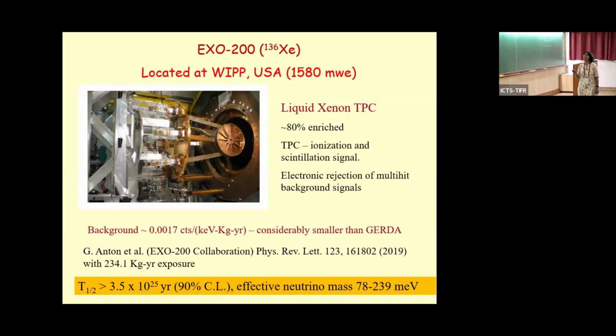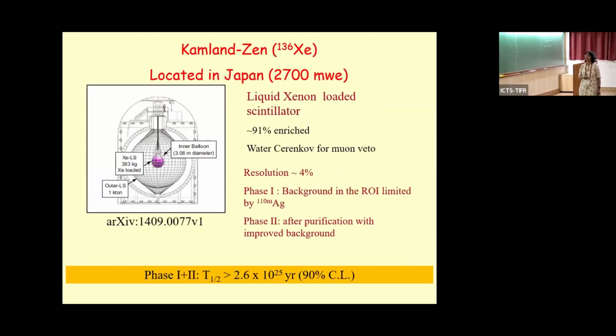Actually, originally when this was proposed, they had a second step to it, because the xenon, when it decays, goes to barium, and barium has a metastable state. So the idea was to have a laser excitation on the barium. When you get an electronic signal that you have a double beta decay, shoot your laser on the barium, excite it, and do that. That would have been a very positive identification. Some tests were done on that, but I think right now there is nothing further on that. But they have the next step called nEXO, that is the 1-ton experiment planned.